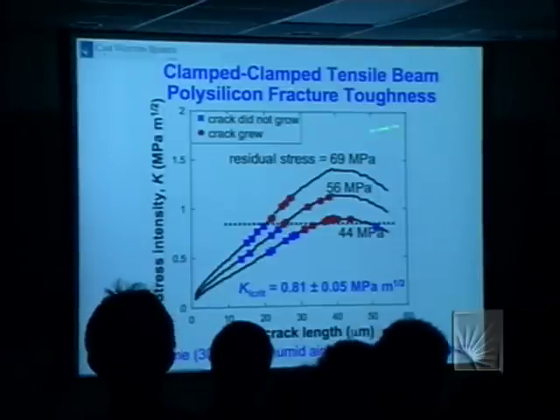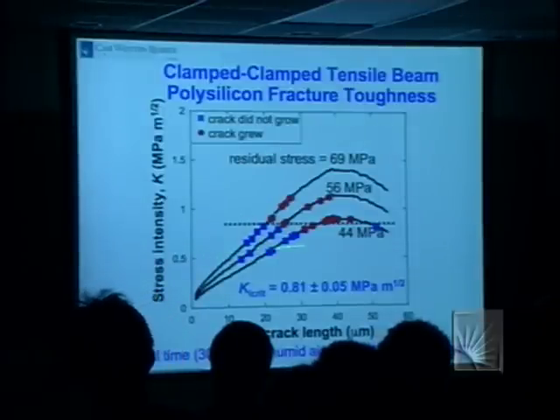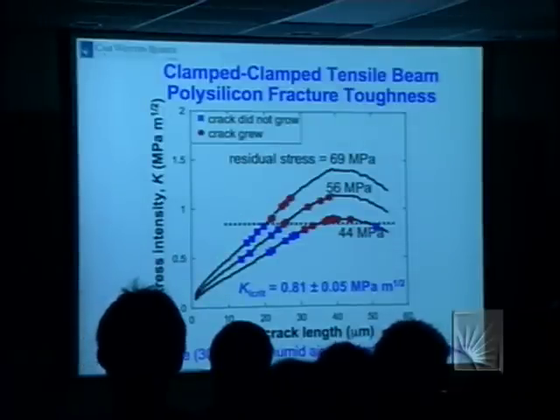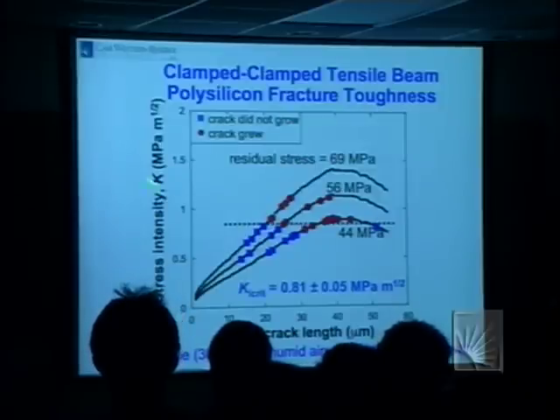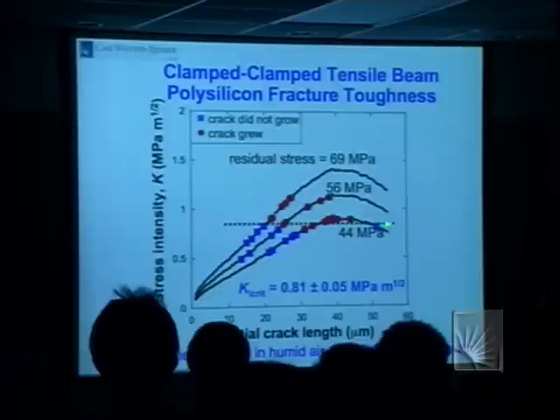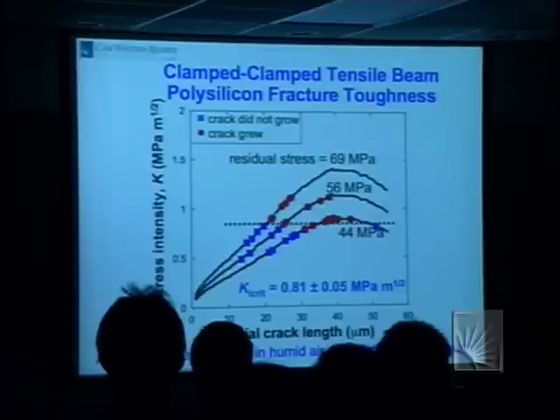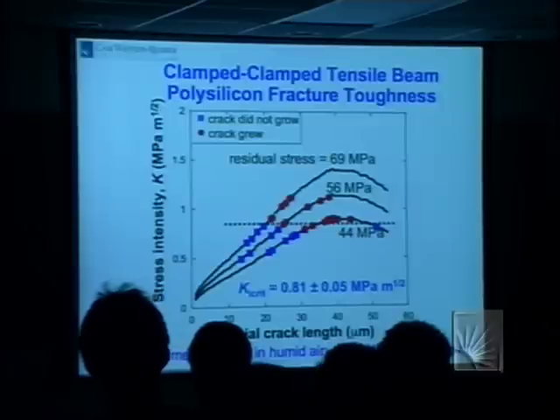And the blue symbols are devices that didn't fail, and the red ones fail. And this is what we take the fracture toughness, K1C, to be, upon release in aqueous HF solution. It'd be very hard to get this measurement with this precision in any other way.